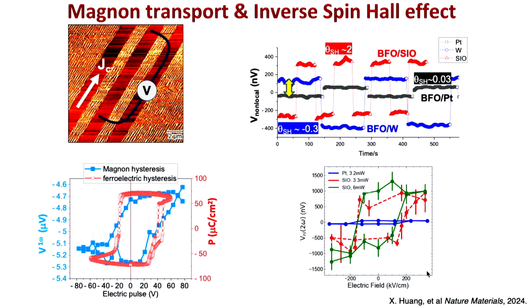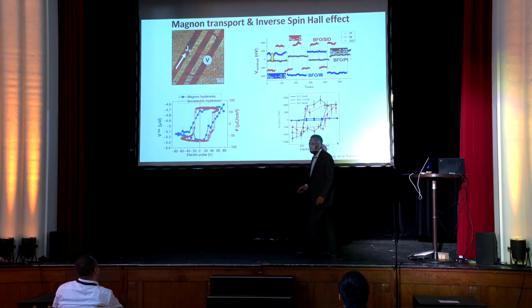So these red stripes are basically the metal layers, strontium iridate, where we do the spin Hall measurement. And what you can see is that compared to platinum, which is the open squares, the black one, and tungsten, the spin Hall angle is about 10 times larger for the strontium iridate compared to platinum. We think it can be significantly larger than that as well. Nobody knows the limits of these.